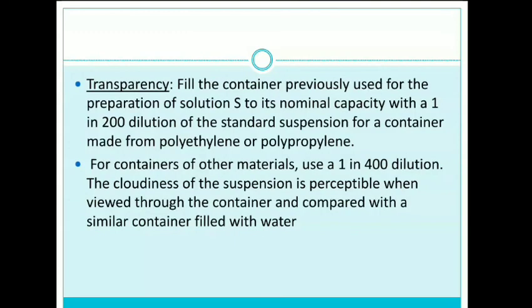The next test for parenteral preparations is transparency. Fill the containers previously used for the preparation of solution S to their nominal capacity with a 1:200 dilution of the standard suspension for a container made from polyethylene or polypropylene. If the containers used for this test are made of materials other than the above, you have to use a 1:400 dilution. The cloudiness of the suspension should be perceptible when viewed through the container and compared with a similar container filled with water.